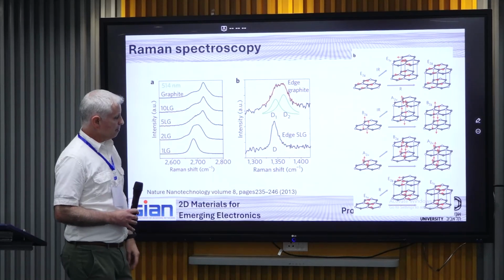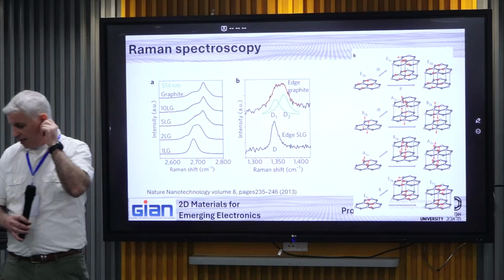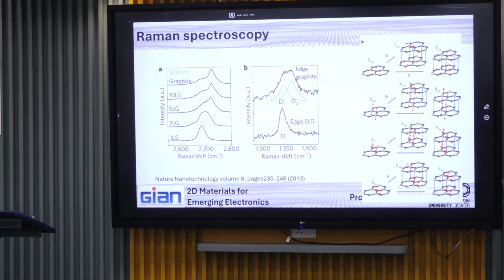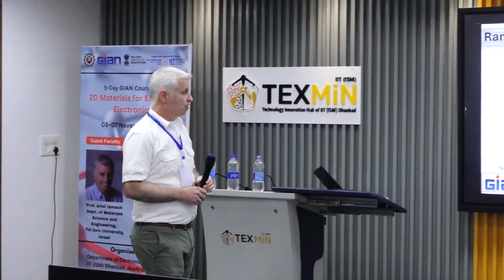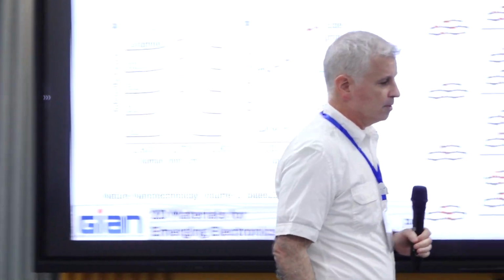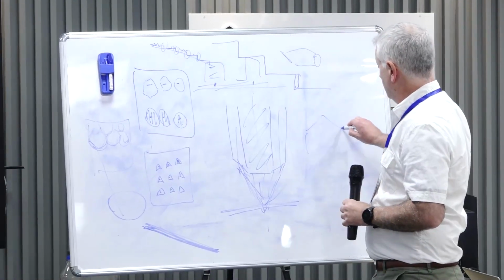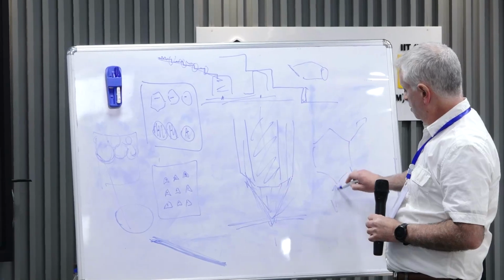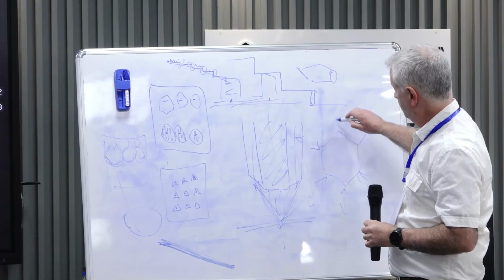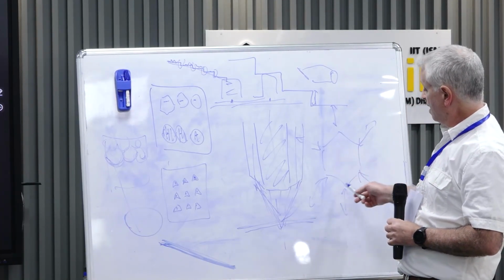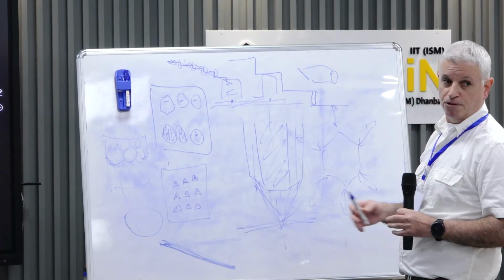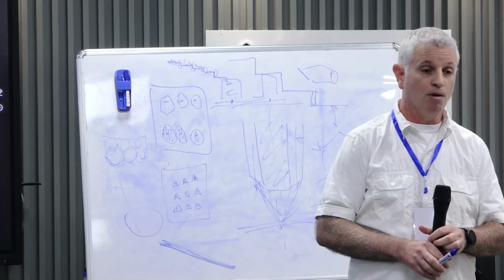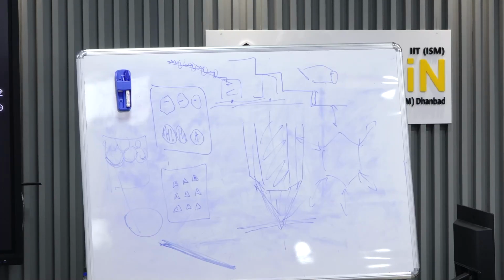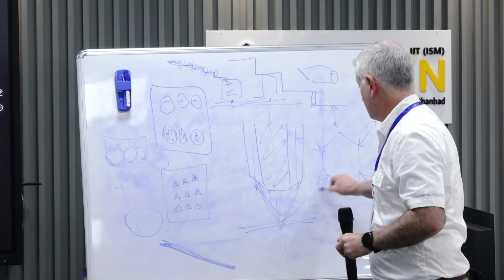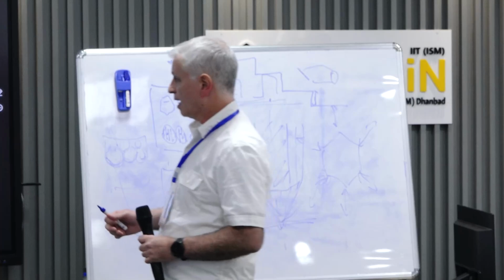On the other hand, the D band, which I didn't show you yesterday, because that spectrum came from a material with no defects. The D band got the D name because it is a signal that is triggered by defects. The phonon mode in the D band is basically the stretching of the hexagon, right? So as a result of that, if the lattice is perfect, they just cancel each other. Therefore, you don't detect any defect. If the sample has very low density of defects, you don't have defect signal. But if you have a defect, say a point defect, then it becomes triggered and active.